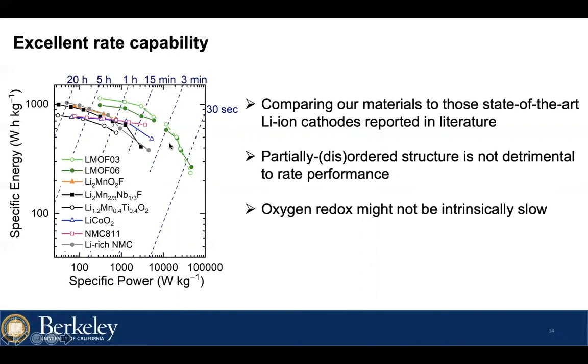So we believe that the disordered system is not limiting the rate performance, as long as we can carefully manage the cation distribution, like in this case, spinel-like order. And also, oxygen redox might not be the intrinsically slow process. But what is the intrinsically slow process?